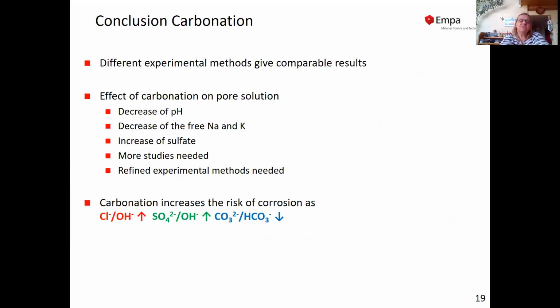If we conclude what we've seen in this carbonation part, different experimental methods give comparable results. The effect of carbonation on pore solution: it decreases pH, it decreases sodium and potassium, it increases sulfate, and I think there are still a lot of things that need to be done in that aspect. Carbonation increases the risk of corrosion, in particular as it increases the chloride to hydroxide ratio.